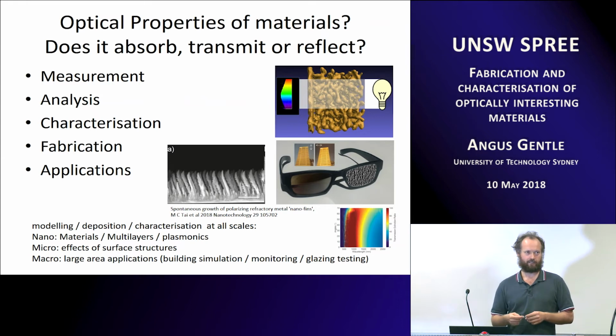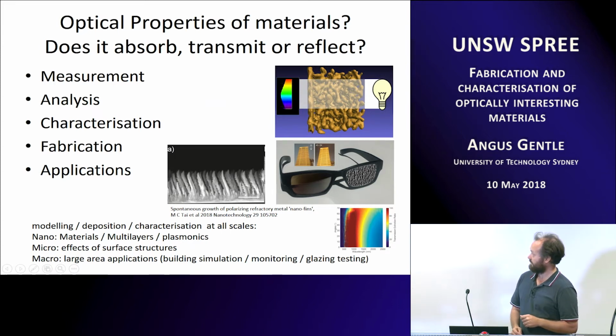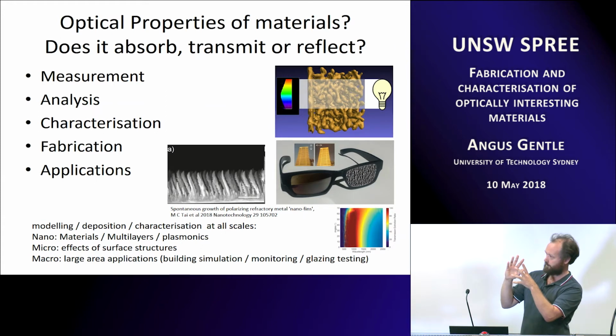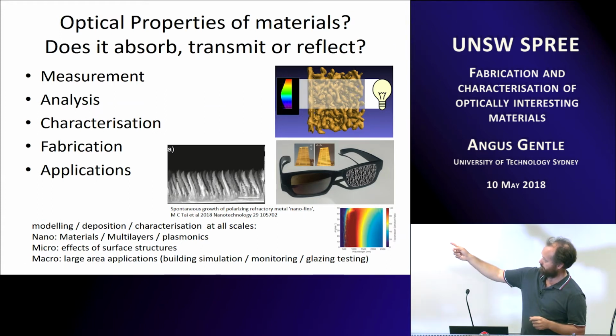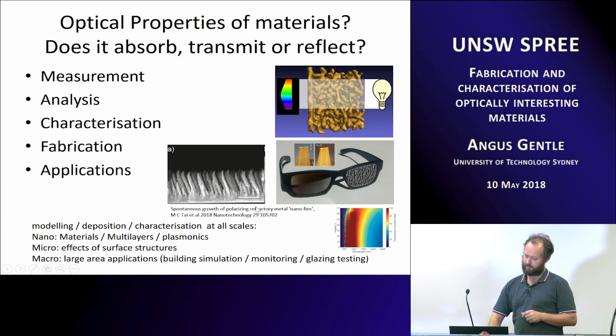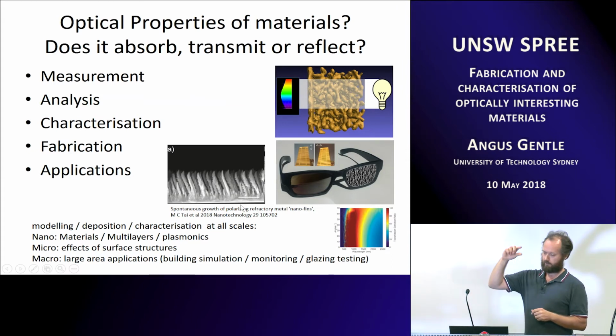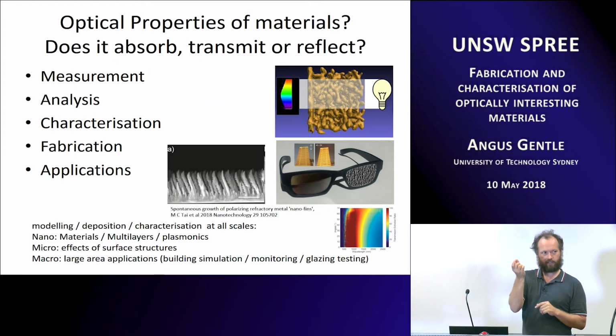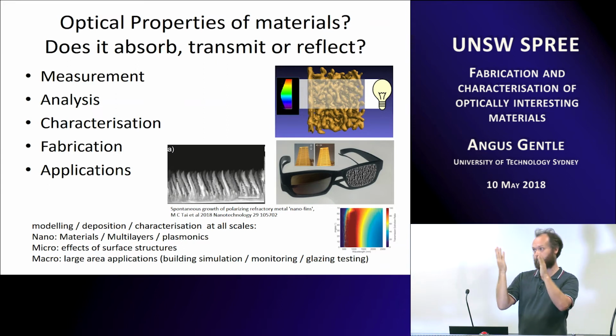And so since then we've also gone, you can also look at how far through you are and what the process is going on by just measuring the current that forms from the aluminium coming out. So that's another one we've been doing since. This is a pretty picture from a paper we put out earlier this year on some self-assembled nanofins. So on the figure A there, that bar is 500 nanometers long. So you've got micron long fins which stick up about 200 nanometers across and 50 nanometers or less the other direction, made out of molybdenum, those ones were.